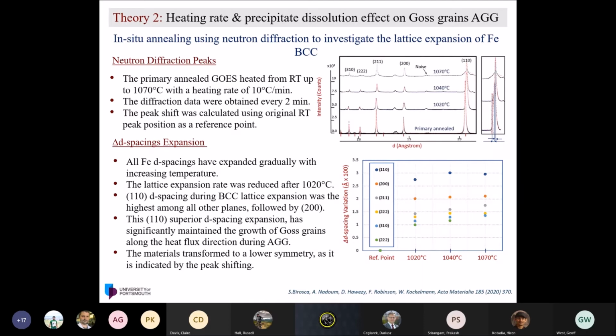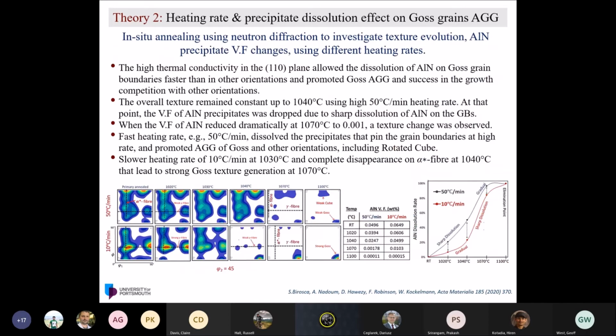But that high expansion rate of the 110 gives us the superiority of 110 D spacing expansion, and that's why we thought that the Goss grain is growing dramatically if the heat flux were applied in the right direction. That's okay, you move to that part, because I wanted to talk about the peak shifting, but I'll talk about it later. Now we try to understand why that happened.